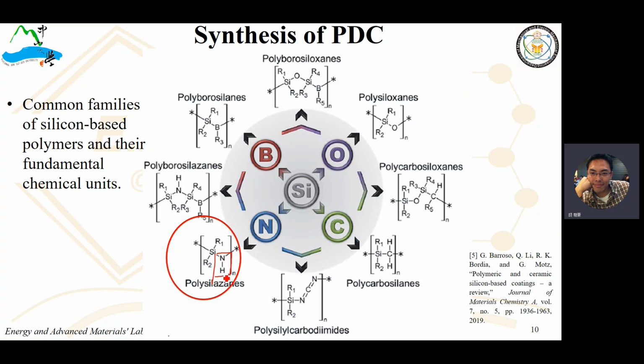If the precursor were a polysiloxane, that would mean we have silicon-oxygen bonds right here. Oh, sorry, I made a mistake, I have to correct it. It's a silicon-nitrogen bond. So it's a silicon-nitrogen bond, and the silicon-nitrogen bond can also be combined with boron. So the precursors depend on the bonding between the silicon and its functional groups.